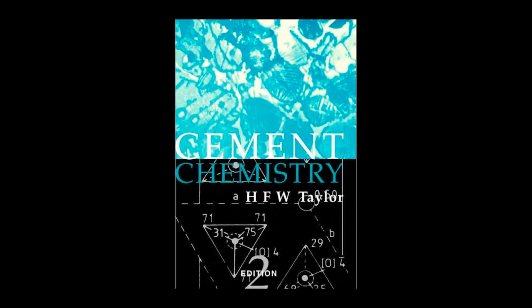We mentioned DEF earlier, delayed ettringite formation, which is the reformation of ettringite that causes expansion in concrete cured at high temperatures. While DEF used to be treated as a standalone failure mode, recent research suggests there's a strong synergistic link with ASR. This connection is a critical and still evolving insight in durability science.